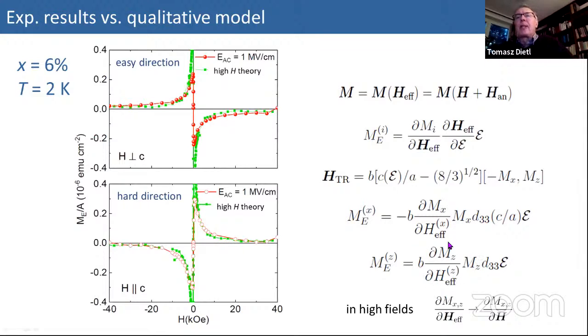And also you can see that in high magnetic fields, when the external magnetic field is much larger than the anisotropy field, actually this is the derivative of magnetization. And these green points are just the derivative of magnetization. So you see that we can describe quite well this effect from the simple theory, where the derivative of magnetization determines the effect. But let's go to weak magnetic fields, what happens in weak magnetic fields.